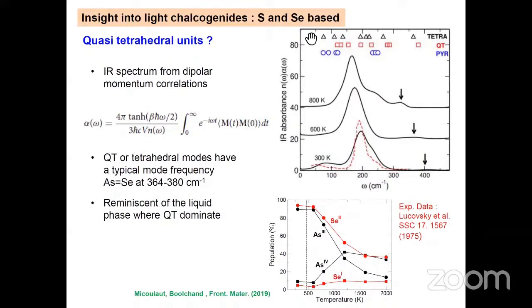But furthermore, if you look at isolated clusters, which might be present in the system, like tetrahedral arsenic or quasi-tetrahedral arsenic, you can see that they have a typical frequency, which is close to 400 wave numbers. And that is also found as a bump in this calculated spectrum. So there might be some features related to defect coordinations in these systems.